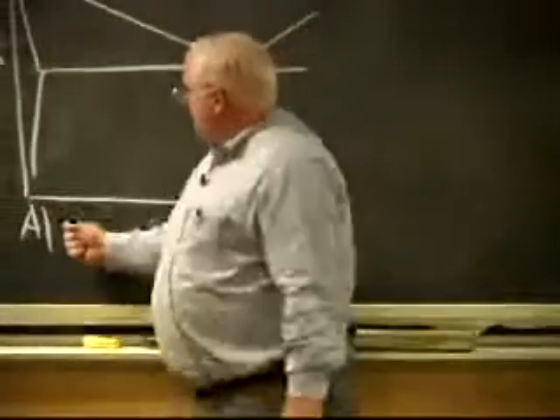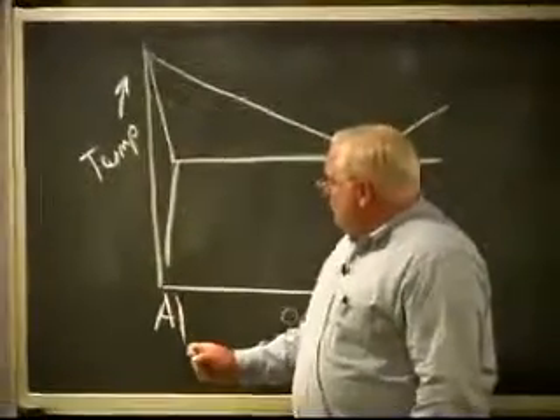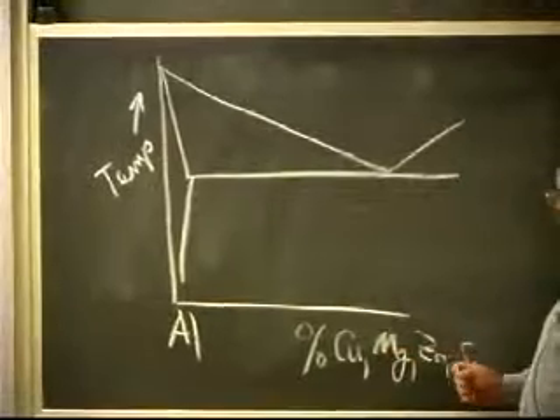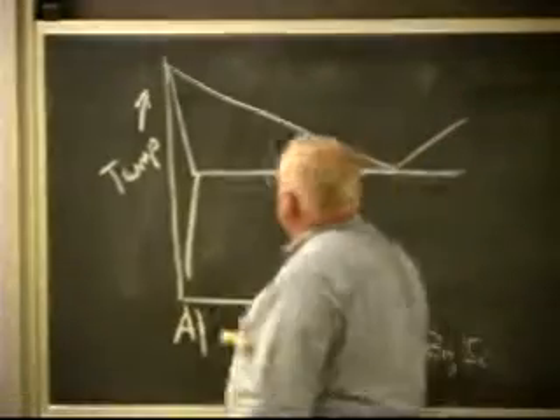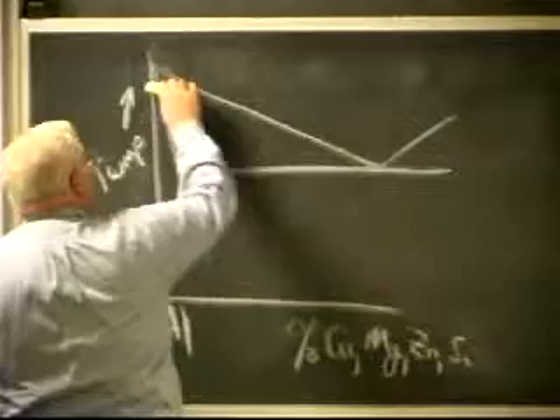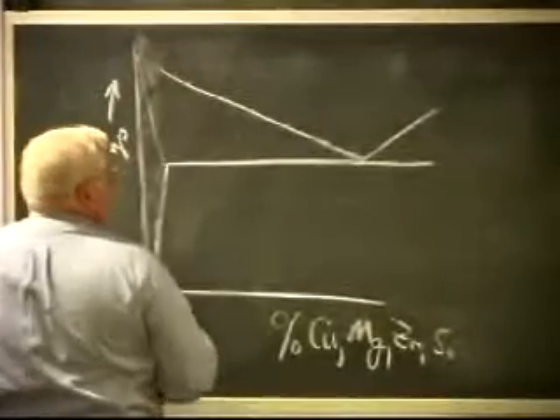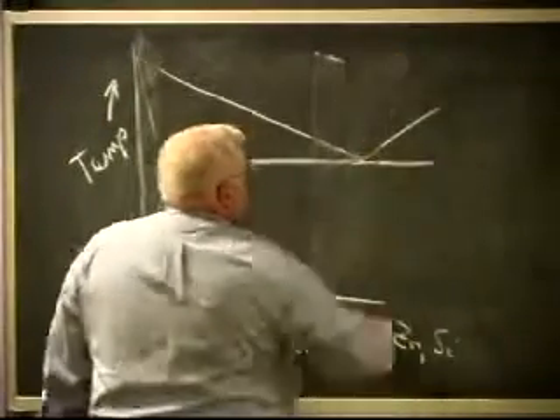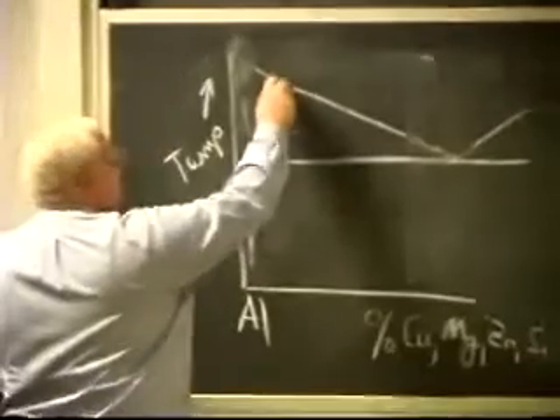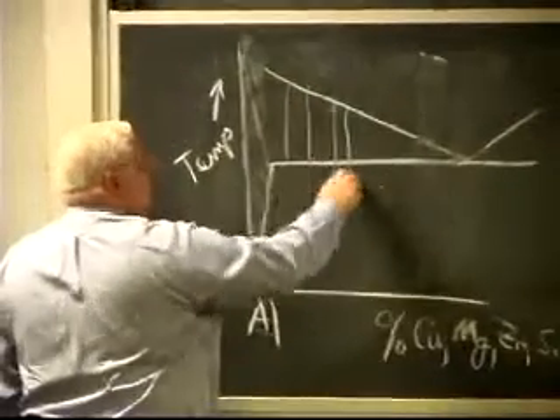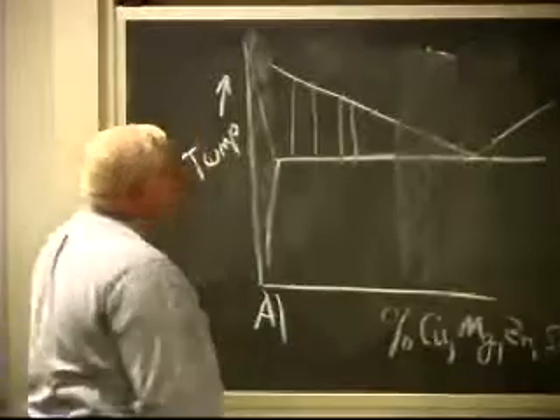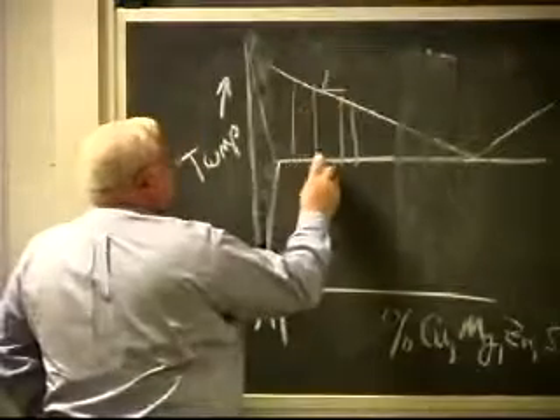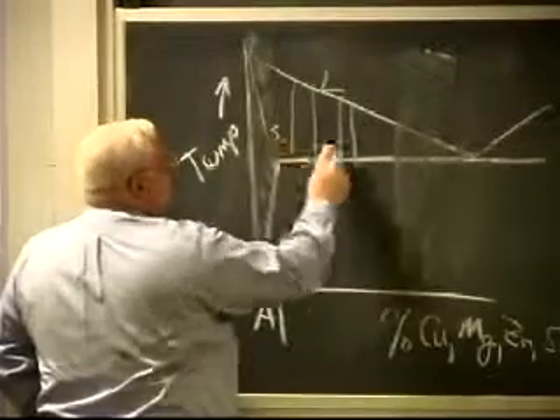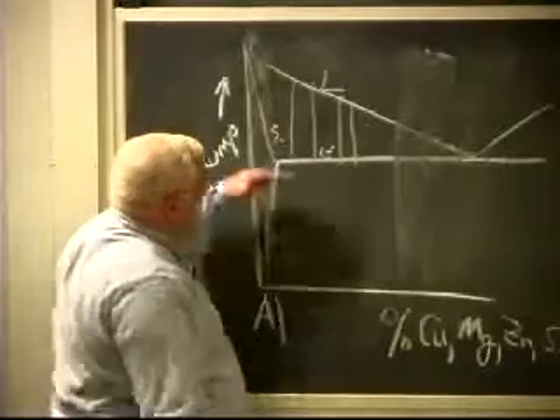Other questions? Okay. We were talking about joining of aluminum, and the thing is, with aluminum you're alloying with copper, magnesium, zinc, and silicon. There's 2 regions that you tend to develop your aluminum alloys. One is over here in the high aluminum alloys, and the other one is over here near the eutectic. You try to avoid this range in here where you have a wide freezing range. This is the liquidus, and this is the eutectic line, and this is the solidus over here. But this is basically where the material becomes solid.